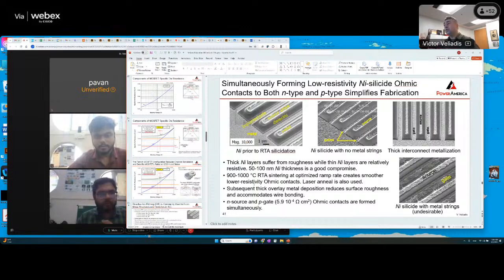If you follow that flow, you will not be able to make competitive devices if you don't thin the substrate. So when it comes to devices that are up to 1700 volts, you need to thin the substrate. Now, once you exceed 1700 volts and you go to 3.3 kV, 6.5 kV, 10 kV, the thickness of the layer that holds that high voltage is basically the majority of the resistance. So you can afford to have a thicker substrate.